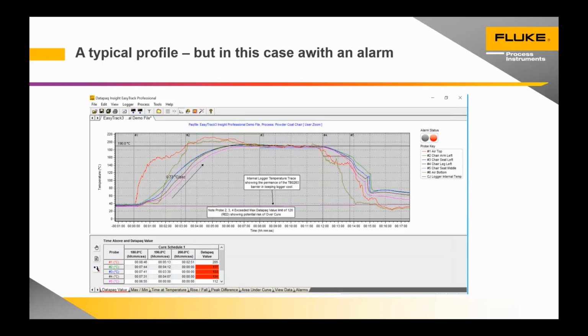Whilst we're looking at the graph, I can see this was done on a 5-zone oven. You can see the vertical lines on the graph here that denote the end of the zones. So if we're looking at a particular feature, maybe an overshoot in temperature, we can see that's happening in zone 2. We see immediately where it's happening in the oven. That speeds up our fault finding.